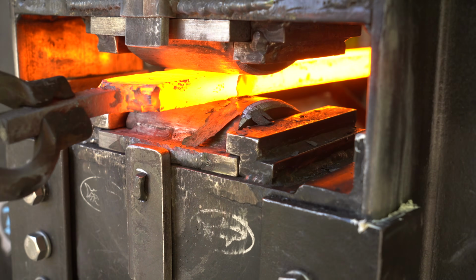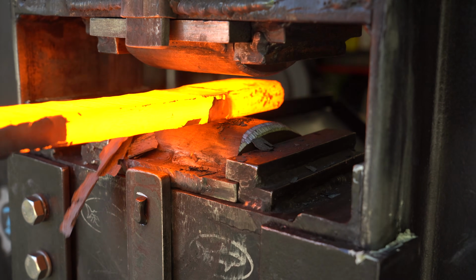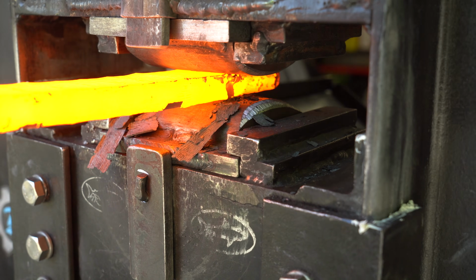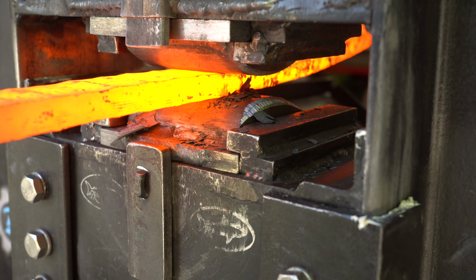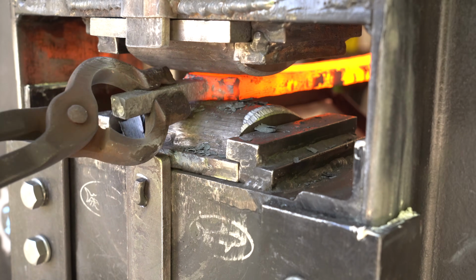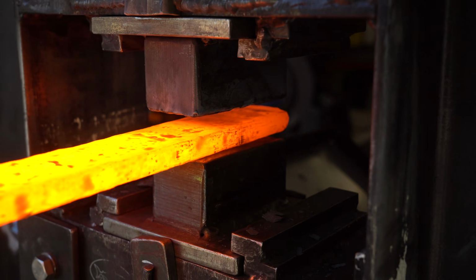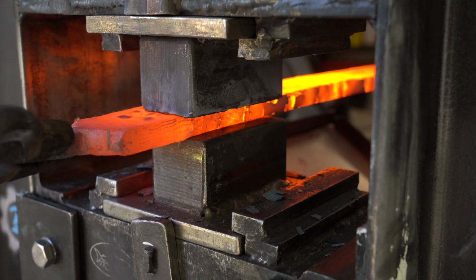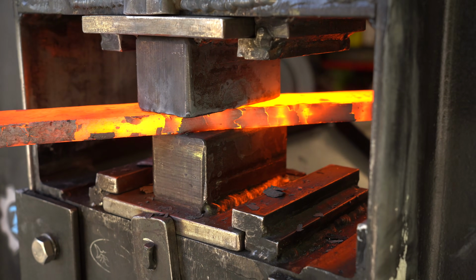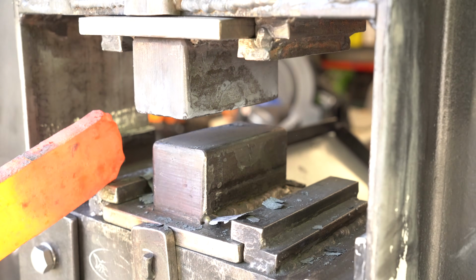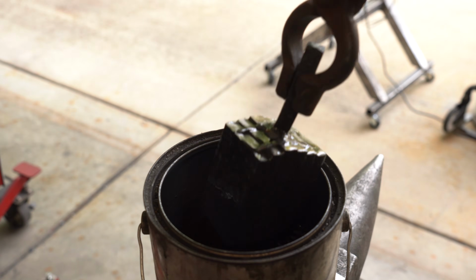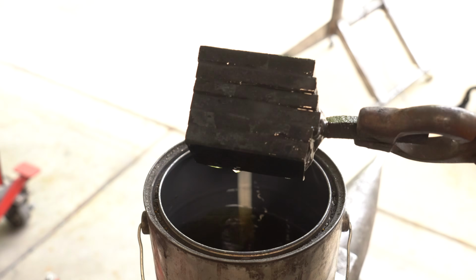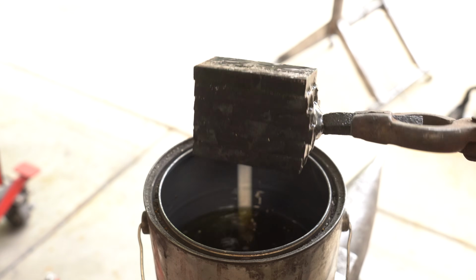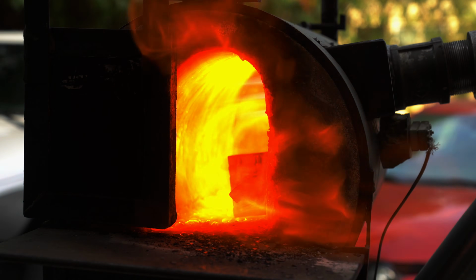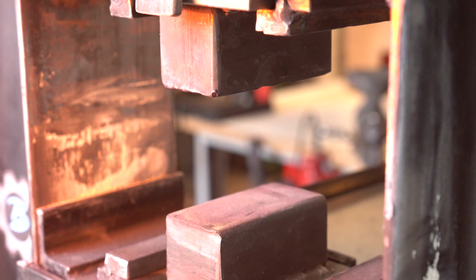This last heat with the drawing dies should give me the length I need, and then I'm going to flatten it out to have a nice flat billet for the restack. Off camera I cut this up, ground all the mating edges and welded it up. We're going to go back in the forge. Also, what you're seeing here is my homemade ribbon burner forge. If you're curious on how to build this, there's a link up in the corner.